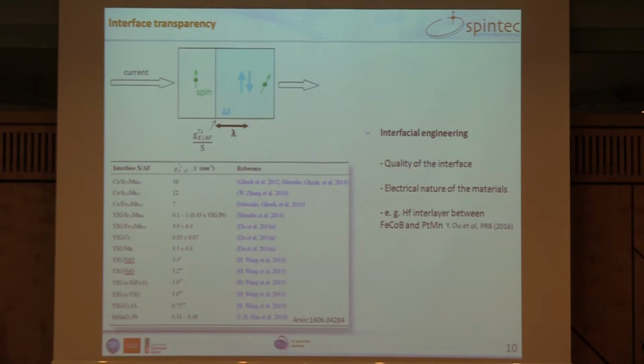I'd like to stress also that there is a lot going on in interfacial engineering. So it's possible to have access to this parameter by spin pumping, but this parameter is very important even when you do spin orbit torque switching or these kinds of experiments. And there is a very nice paper, not from us, where these people have added hafnium in between cobalt iron boron and platinum manganese, and they could increase the torque efficiency by a factor of 10.